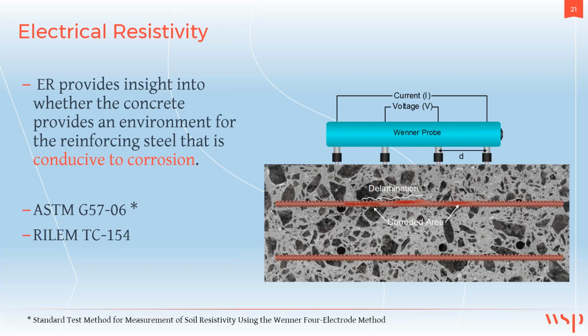And the test method is, in this particular case, using a 4-point probe. A current is passed between the external points of the probe, and the voltage is monitored between the internal points. This is done in the alternating current domain, and the resistivity can then be determined. So higher resistivity means more resistance to the passing of current and therefore less likelihood of supporting corrosion.